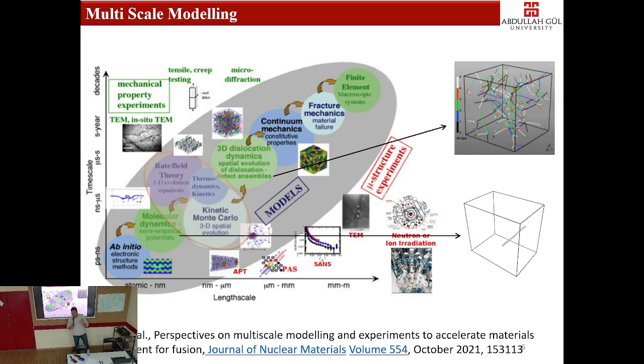Anyway, I just wanted to explain some of the dislocations to you. I'm going back to hydrogen embrittlement. So here, what we need is a mobility law for dislocations. And now when I say dislocation, you can ask which dislocation: edge dislocation, screw, Shockley partial, Frank partial, stair rod. These are all different kinds of dislocations. And for this study, we focused on edge dislocation.